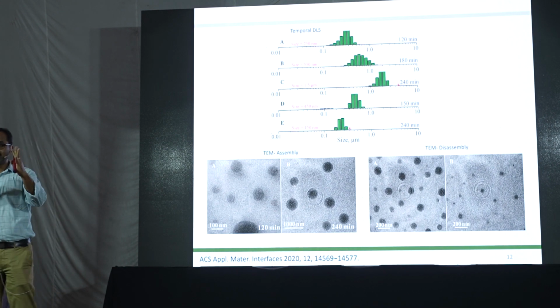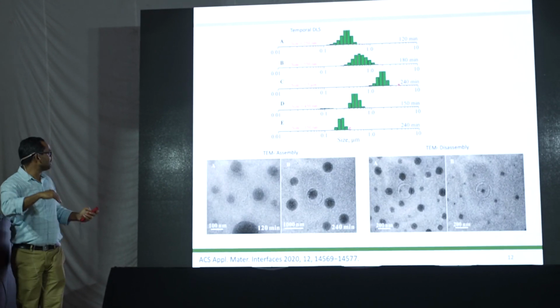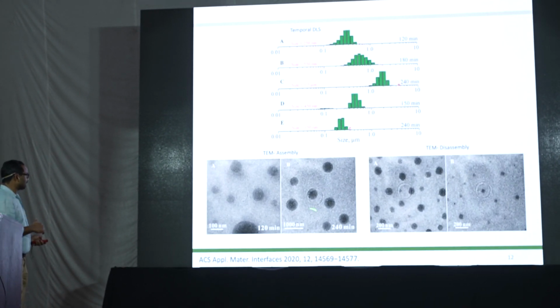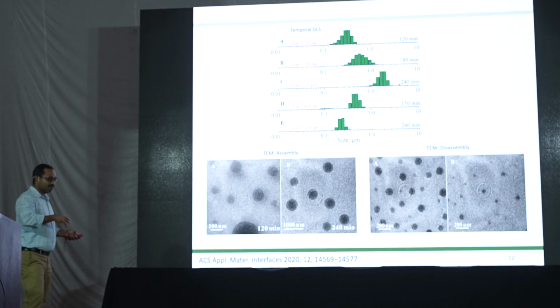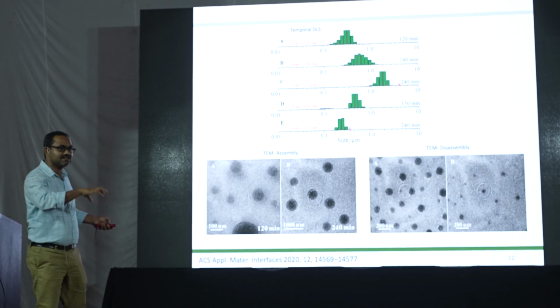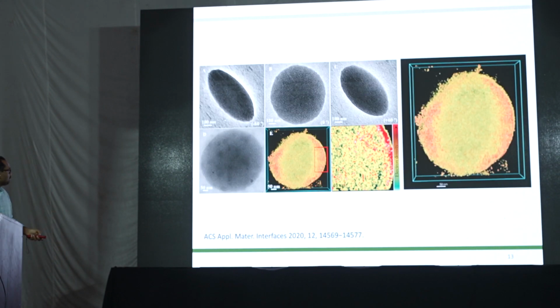In presence of UV light, this superstructure size is increasing, but when you do a visible light illumination, you can see that this is again decreasing, and this is a large area assembly. You can see while assembling, all these structures are almost uniform in assembly, but when you disassemble, we can see that these nanoclusters are disassembling and form small structures and finally form individual nanoclusters.